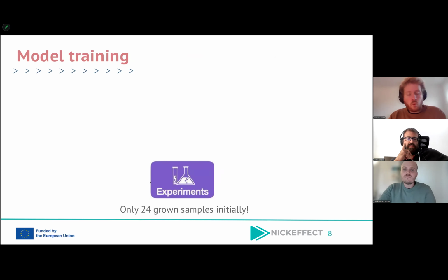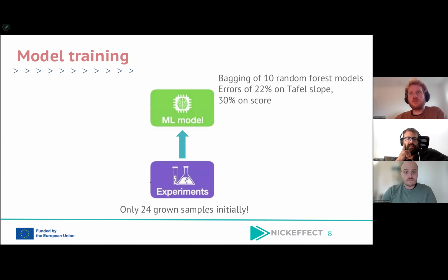And so what we did exactly is we started from the experiments that UAB had done. They had grown 24 samples for which they had the LSV curves. So it's not a lot, but still it can be used to train a machine learning model. In this case, it was a bagging of random forest models, because random forest works quite well when you don't have a lot of data.